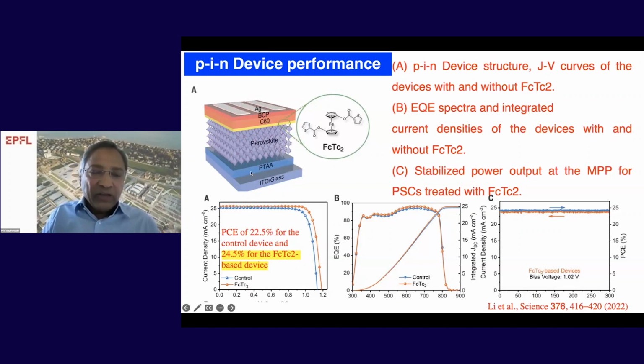You have a conducting glass, and then we deposit a hole transporting material. In this case, I have taken the example of PTAA, but many groups now are using nickel oxide as a hole transporting material. Then you deposit perovskite, and then a very thin passivation layer, thiophene-containing ferrocene molecules, which act as a passivation layer, followed by C60, the electron transport layer. And then you have BCP, a passivation layer which prevents the silver migration or formation of a silver complex. So this passivation buffer layer is important in order to get the highest efficiency.